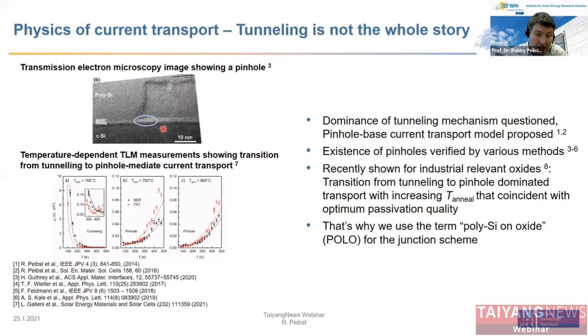This was shown nicely in a recent work of IMEC, where they investigated the specific contact resistance of this junction scheme as a function of the measurement temperature, and for differently annealed samples, as you can see here. Samples annealed at 700 degrees, which is a rather low temperature for this technology, show a decrease of the contact resistance upon increasing measurement temperature. This is expected for tunneling transport. But if you have a higher annealing temperature, then the behavior is opposite. The contact resistance is increasing, as expected for pinhole-mediated transport.